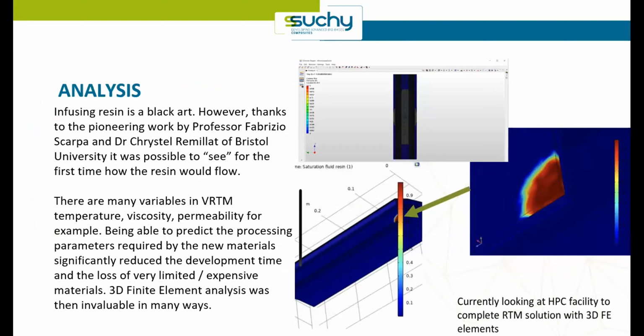At the same time, of course, Bristol were also doing some interesting work, which was very useful in terms of providing data as to how the resin would flow through the mold, because obviously when you're infusing with VRTM, it's impossible to see what's actually happening. So you've no idea where the resin is flowing. And thanks to the work of Dr. Chrystel Remillat of Bristol, and obviously Professor Fabrizio Scarpa, the software that was used here was previously used by Wilson Benesch with Bristol on a previous project, also under the Fast RTM research project. So we were able to actually see the flow of this material as it was introduced into the fiber pack. And as a result of this, we were in a much better position to start infusing the pack with this data. So this accelerated the progress.